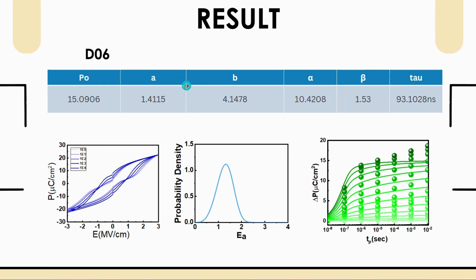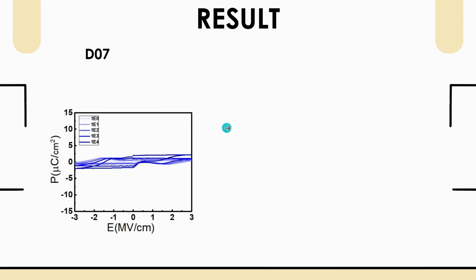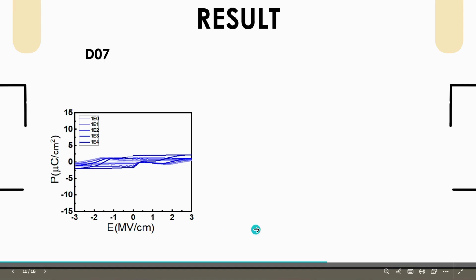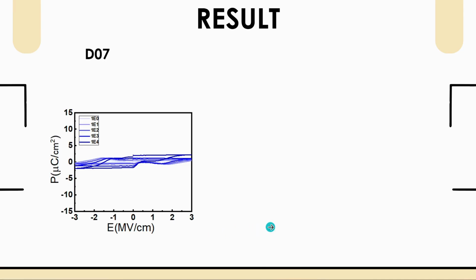D06 also did well. It has similar polarization as D05 and a slightly slower tau zero around 93 nanoseconds. It switched well but seemed to have more trapping, which can slow down the switching and reduce reliability. And lastly, D07 didn't perform well. It had very low polarization, only about 3 microcoulomb per centimeter squared, and almost no switching even after many cycles. This shows that too much gadolinium may ruin the material's ability to switch, and there was some issue extracting the parameter tau zero, so there's no NLS fitting result for this sample.